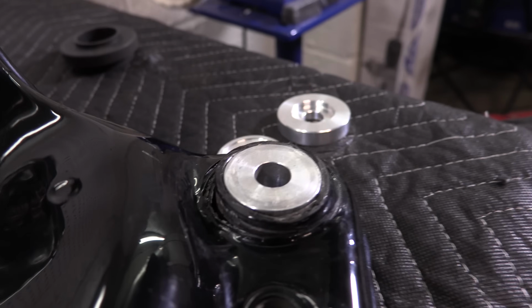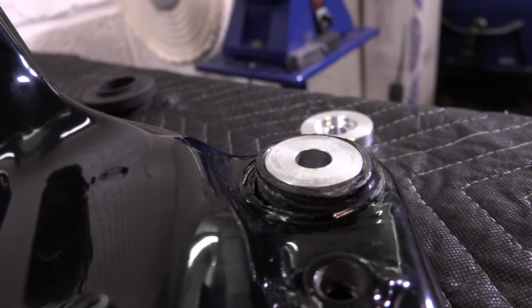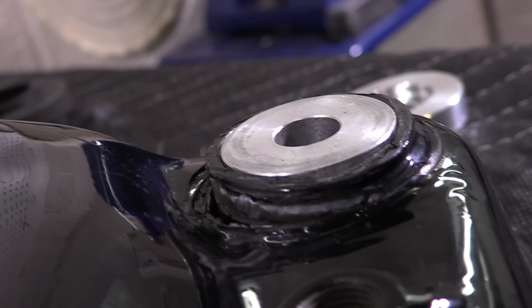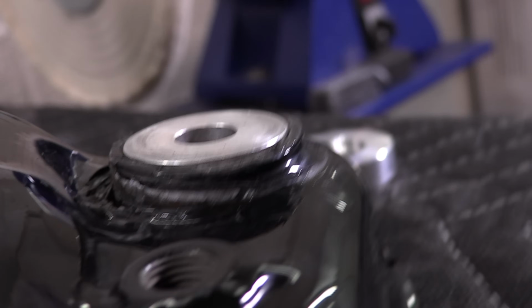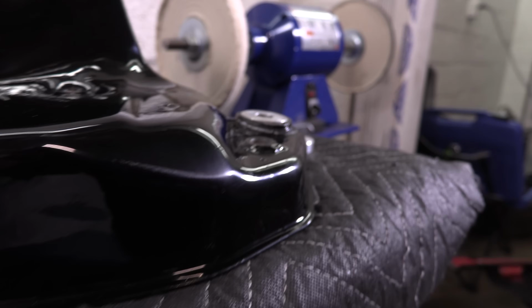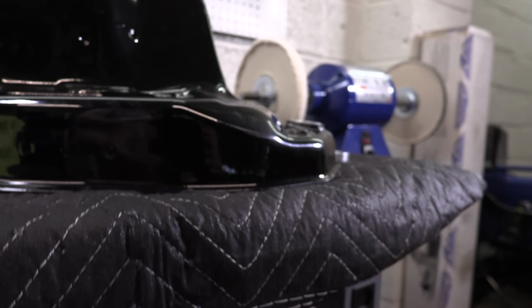The first one that I failed to film the first half hour as I destroyed it. The bushing was 90% of the way in when I discovered that the boss got mangled because my rigging shifted. And that's also when I discovered the camera wasn't rolling. But by then, it wasn't coming back out.